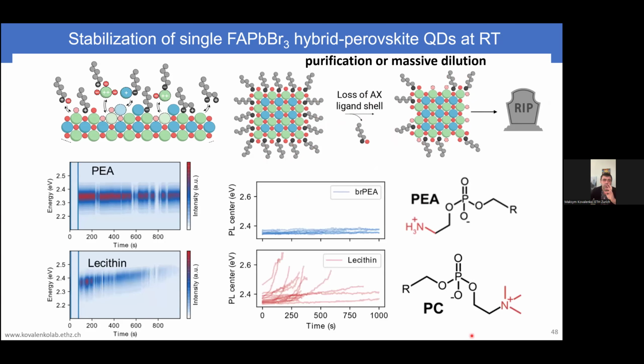And that's what I try to emphasize, that by shifting from just a quaternary to primary ammonium salt and much stronger binding, this already could translate into huge improvement in the survival rate of these dots after such massive manipulations, dispersions and everything. So you see statistically that these are the spectra from single dots over time, and you see that they are retained way better than the best ligand before. So now, and that's at room temperature for hybrid perovskites, which we could not even study before.